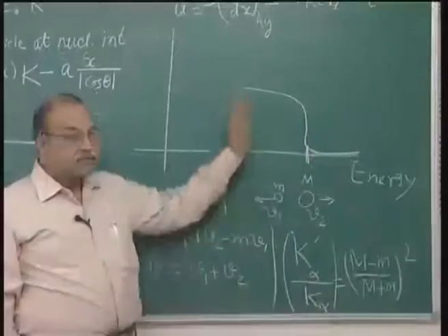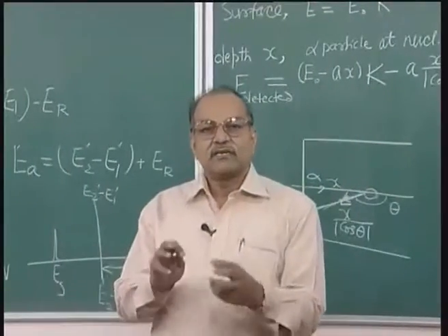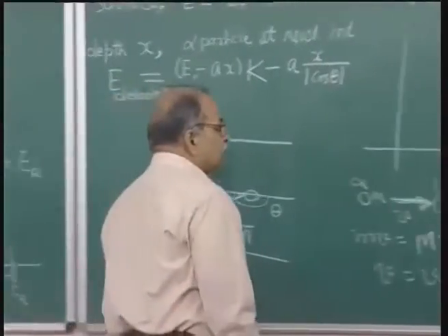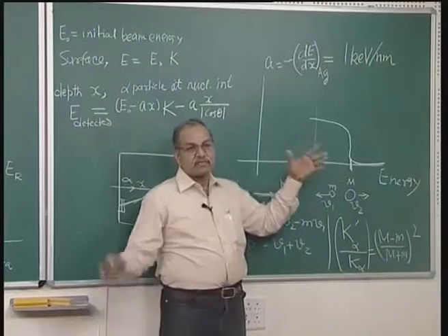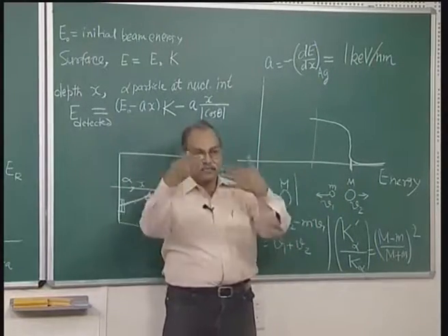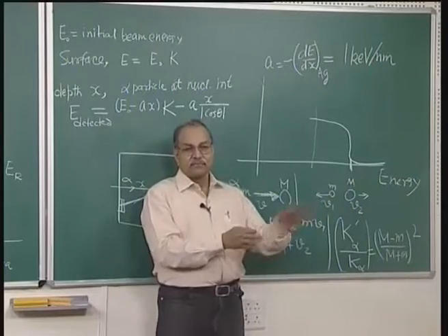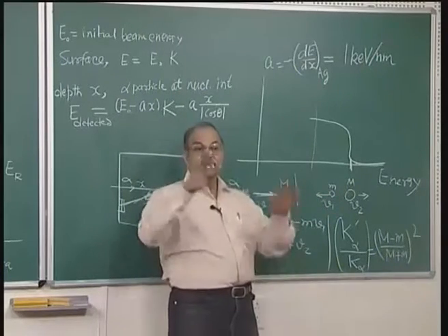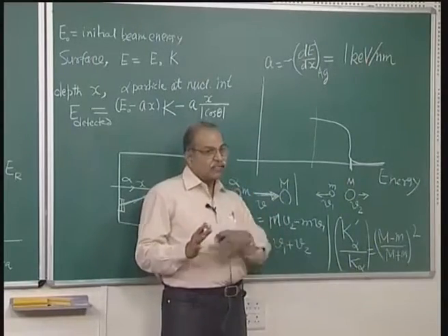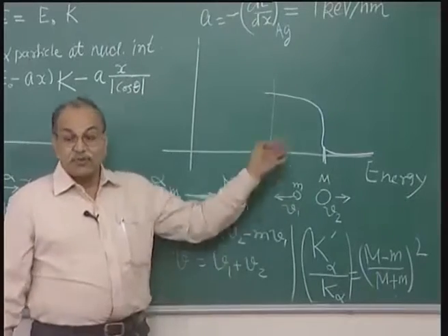and then this height, that depends on how many counts I am receiving, that depends on the cross section and other things, right. So, normally cross section decreases when energy is increased. If you remember that Rutherford equation, Z1 Z2 divided by epsilon naught etc., and energy comes in the denominator, and the whole thing is squared. So, with the same concentration, lower energy will have larger cross section and counts will be larger. That is why it is slightly going up, if the concentration is same.